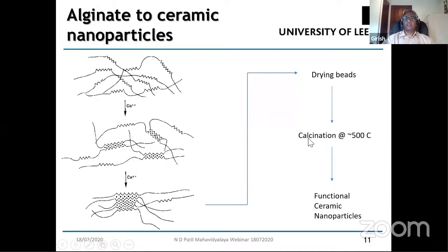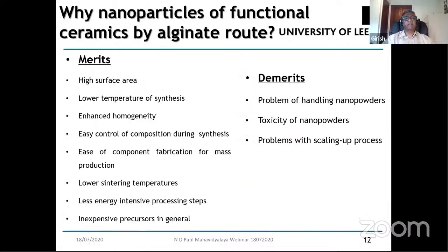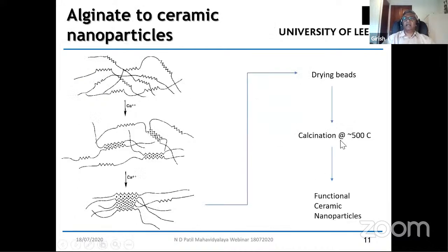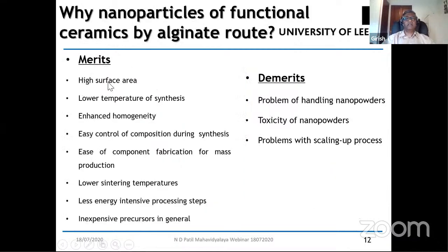It's interesting to note that in most cases, the calcination temperature that we have found for various materials is always around 400 to 500 degrees Celsius. Now, what are the merits of using this particular method? The merits are that it produces consistently high surface area nanopowders, typically in the range of 10 nanometer or somewhere around there, even after calcining at such high temperatures, 500 degrees Celsius. The nanopowders that are produced are consistently in the range of 10 to 20 nanometer.